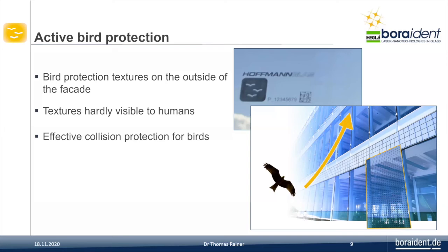There's a second possibility: if you have no coating on the outside of such a window, then it's possible to print with the laser such a pattern on the glass facade, as you can see here in this example, and then the birds don't hit this glass. And so we can avoid this effect that birds are killed at the facade.